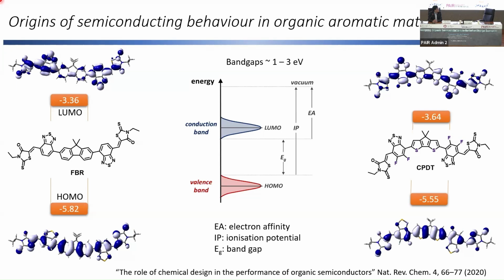And of course, the most common reduction reaction you can think of is a proton to hydrogen. So hydrogen evolution from water. So what we're trying to do is inject from an electrode would be electrochemical, but we're using photons in order to generate our electrons. And we do that by having a heterojunction structure where we take an exciton and then split it into a hole and an electron. When we have the electron in this LUMO, then we can undergo reduction reactions to form hydrogen. And at the other end, we're oxidizing water to oxygen. And these are ways in which we can think about solar fuels.